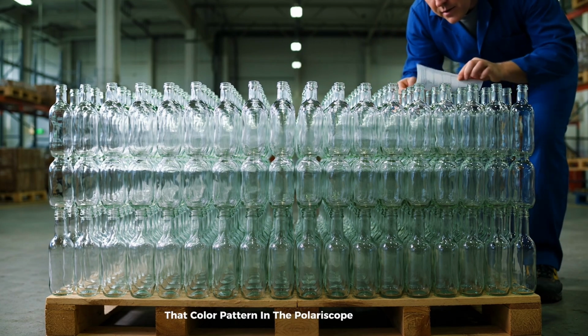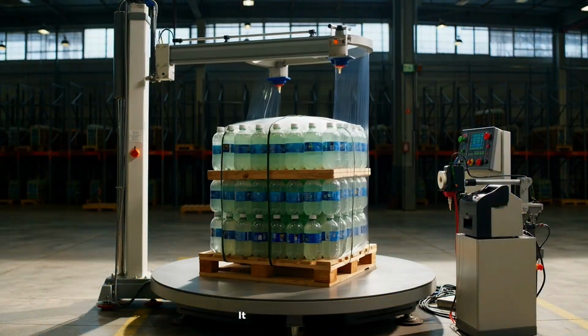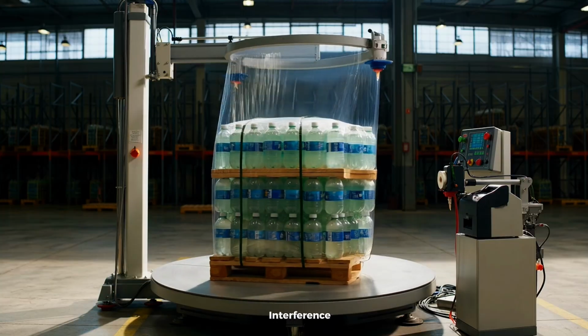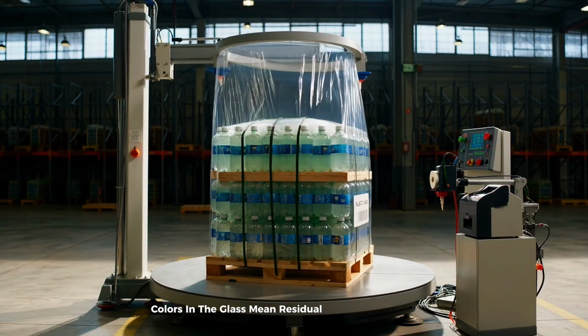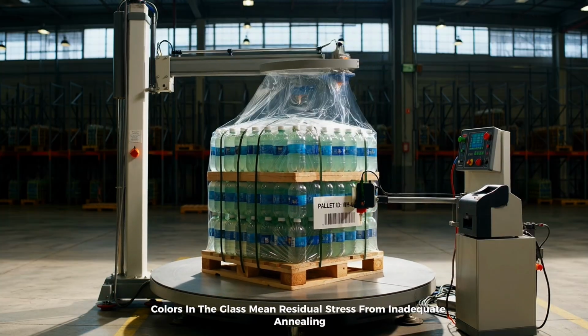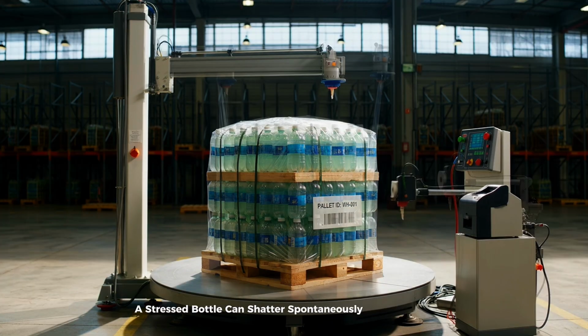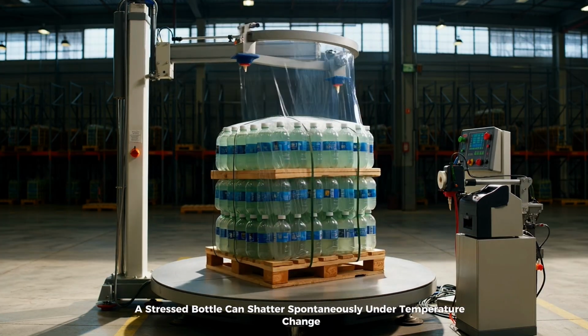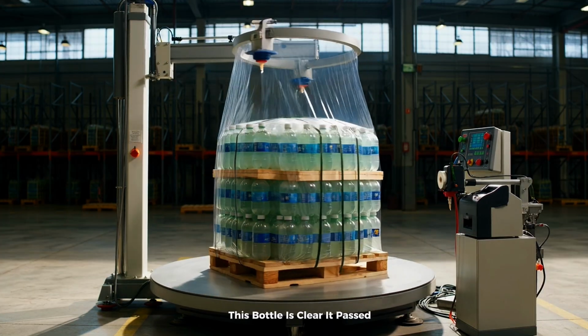That color pattern in the polariscope is not an effect, it is a warning. Rainbow interference colors in the glass mean residual stress from inadequate annealing. A stressed bottle can shatter spontaneously under temperature change. This bottle is clear, it passed.